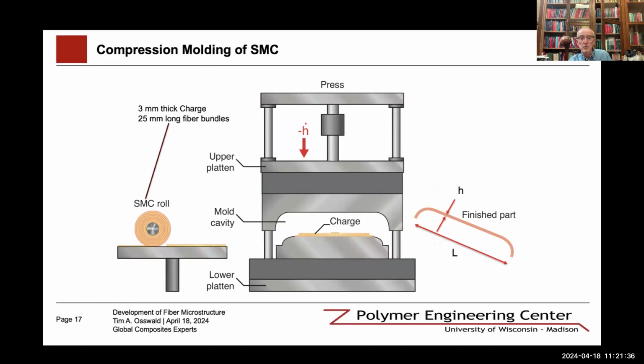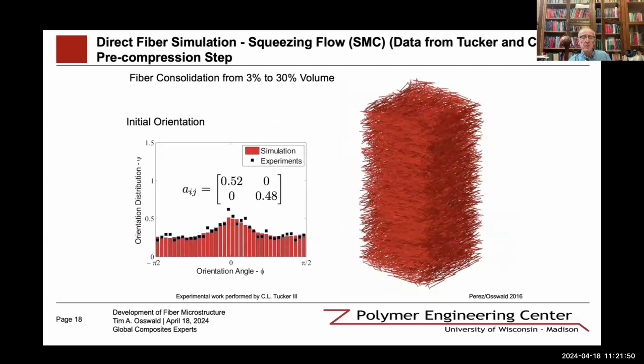We can also use this in compression molding. Compression molding is when we simply cut charges, place them in the mold, and then squeeze them. This would, of course, also lead to fiber orientations. If we do, for example, a charge in unidirectional flow, as the work that Chuck Tucker and Larry Chen did in the 1980s, we can start out with an initial orientation.